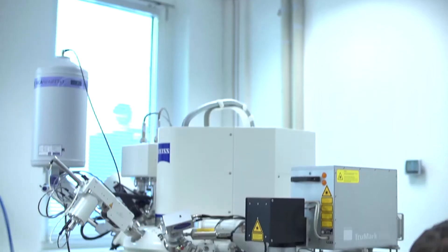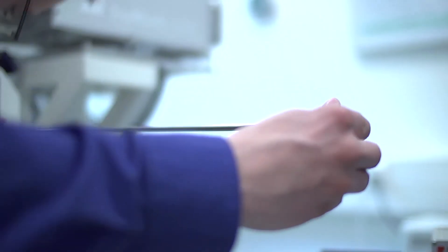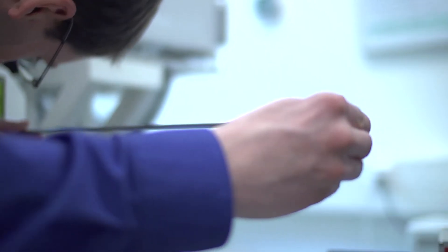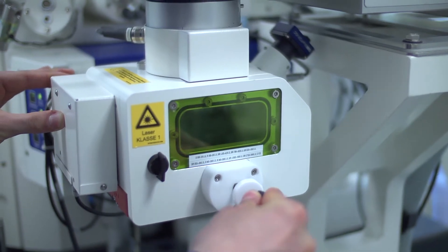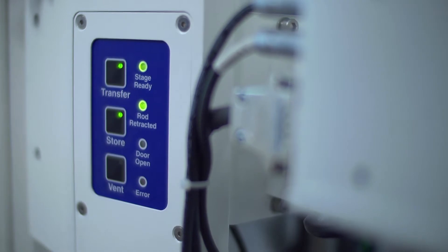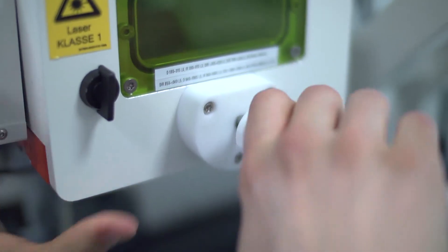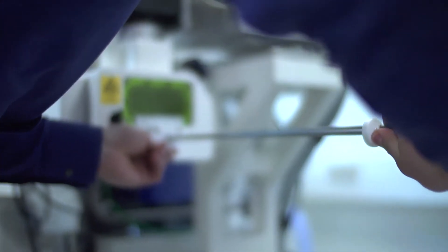The ESB detector was also implemented in software developed together with Zeiss for endpoint detection. That's important if you want to have a TEM lamella of a certain thickness. When we are after root causes of failures in microelectronics components, we usually start with some non-destructive testing, including X-ray microscopy, scanning acoustic microscopy, or lock-in thermography.